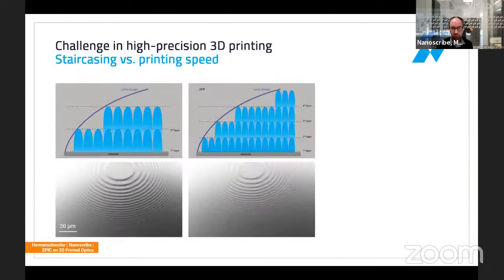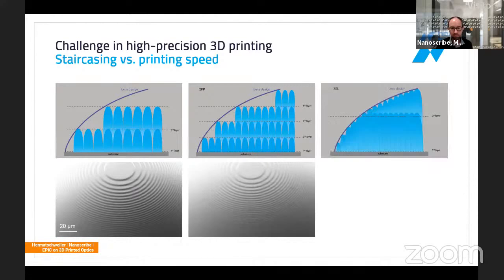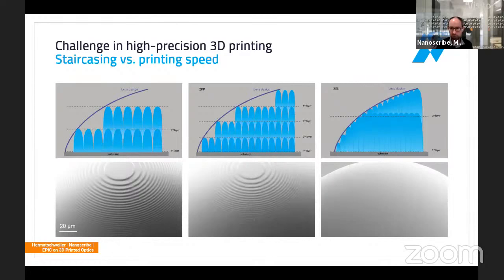You can, for instance, get rid of concentric rings that you typically find when you, no matter how fine you slice an object, if you have a hemisphere in the center zone, which is the most important zone of a micro-optic, you will always find concentric rings. For two-photon grayscale lithography, you can completely get rid of it, and this results in baby smooth surfaces, so sub 10 nanometer surface.